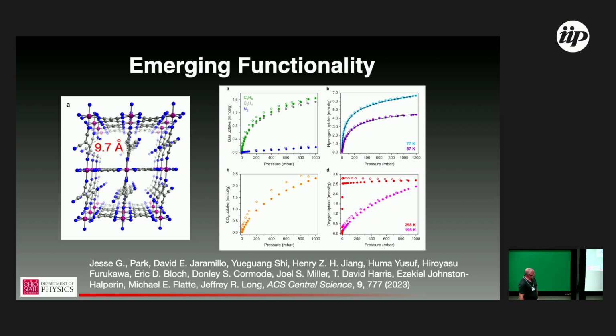But the last thing I want to mention is to come back to this porosity. Our collaborators in the Long group at Berkeley have done a gas adsorption measurement where you take these various gases, increase the pressure, and see how much of the gas gets adsorbed into the porous structure, and you can use that to calculate a pore size of 9.7 angstroms. That didn't mean anything to me as a number, but in talking to the chemists, they got very excited about it because that's a porosity comparable to zeolites. If you're not familiar with that class of materials, that's what people generally use as a gold standard for highly porous materials for gas storage, filtering, and cleaning.